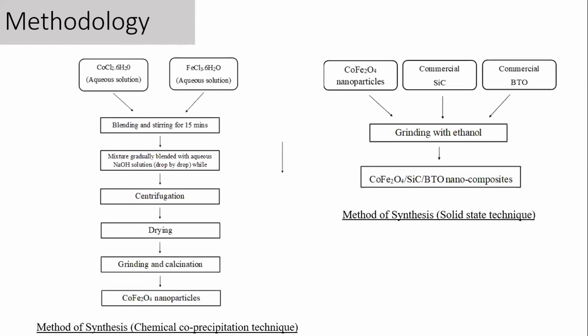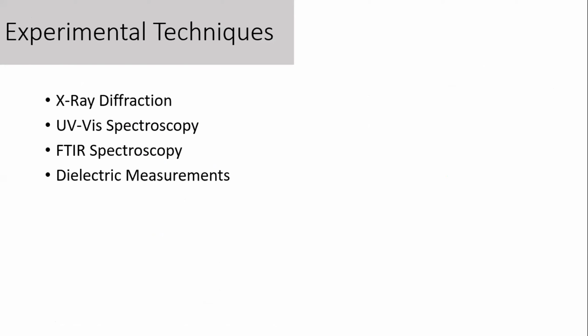The cobalt ferrite nanoparticles were then used to synthesize a nanocomposite mixture with silicon carbide and barium titanate. For that purpose, as already mentioned, we used commercial silicon carbide and commercial barium titanate. We ground the mixture with ethanol for 2 hours, and what we achieved was cobalt ferrite, silicon carbide, and barium titanate nanocomposites. Now I'll go into the following experimental techniques one by one.